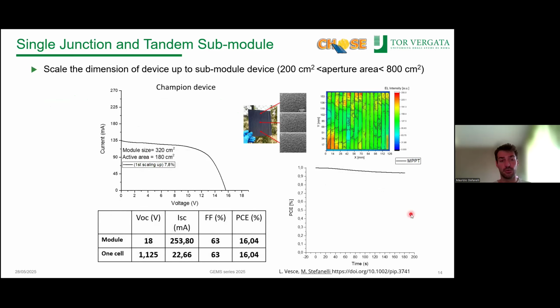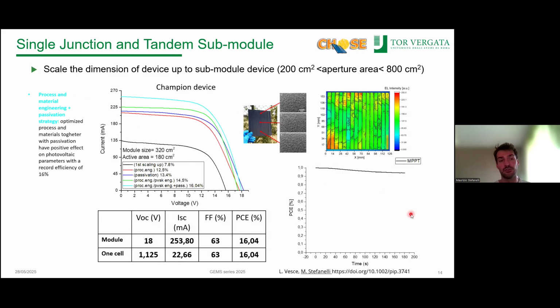So I showed you the first optimization with the process engineering. The second one, the passivation on the surface of our 3D perovskite, and then the solution tailoring of the perovskite, merging all of them together. The optimized process and materials together with the passivation have a synergic effect on the photovoltaic parameters, boosting the efficiency of the best module that we got to 16.04%. That is quite huge for this kind of size.